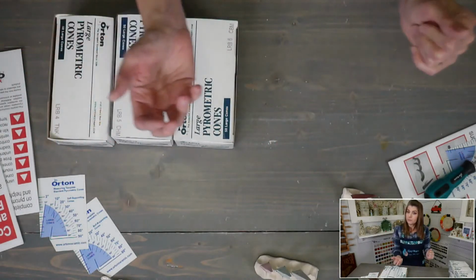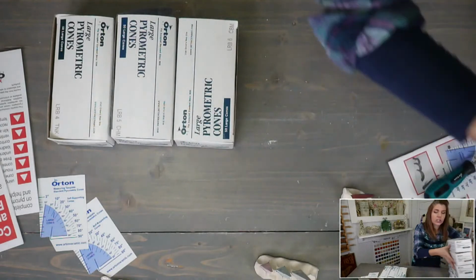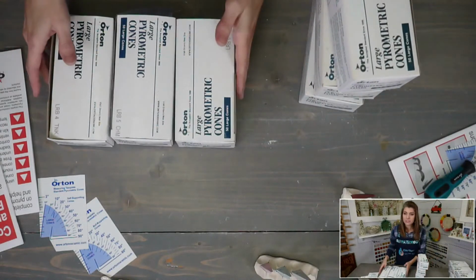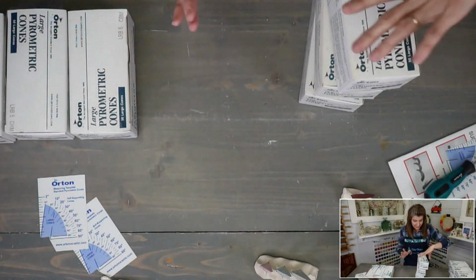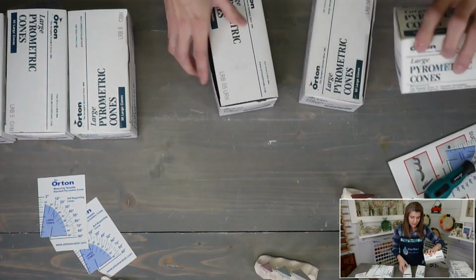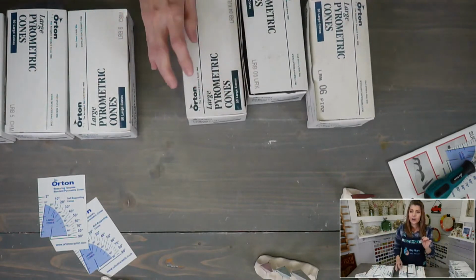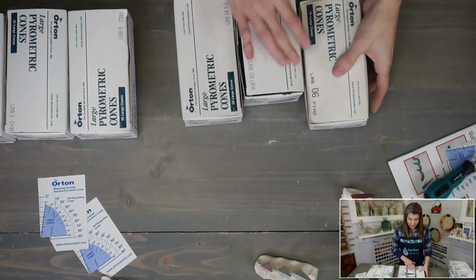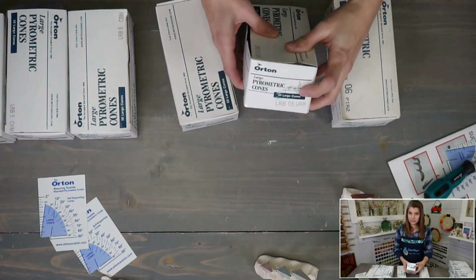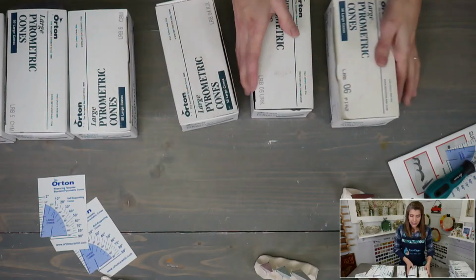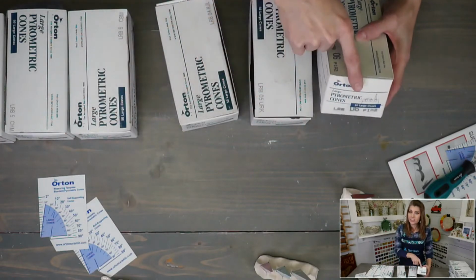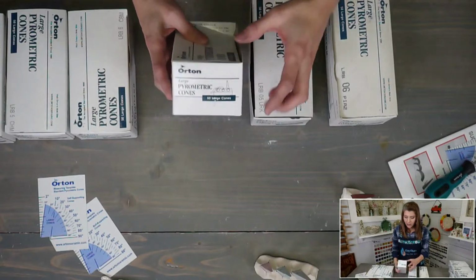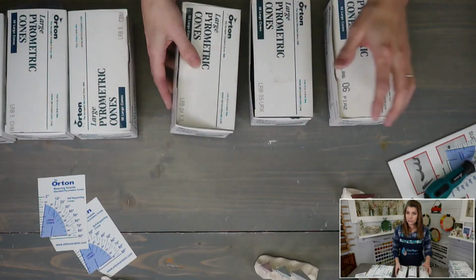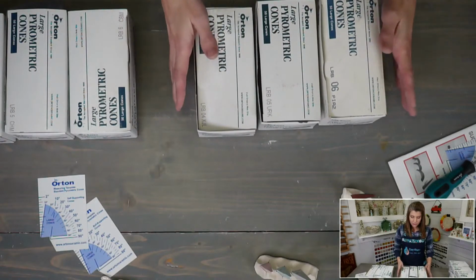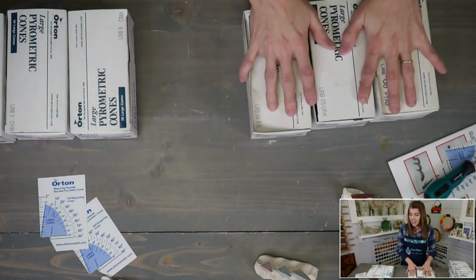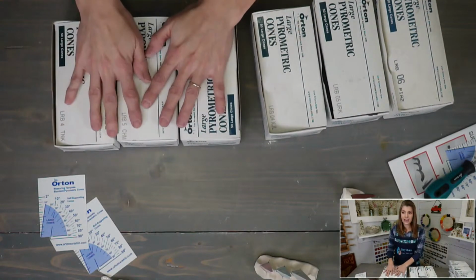Let's do the same thing for bisque firing. I bisque fire to cone 05. Some people bisque fire to cone 04. That's up to you. Now remember, when we are doing the O's, it's negative. So that means here's my 05, negative 5, right? So I need 1 cone cooler, that is 06, and I need 1 cone hotter, that is 04. So this is my set of cones for making my bisque fire packs, and this is my glaze fire packs.